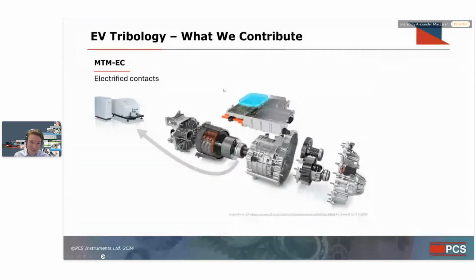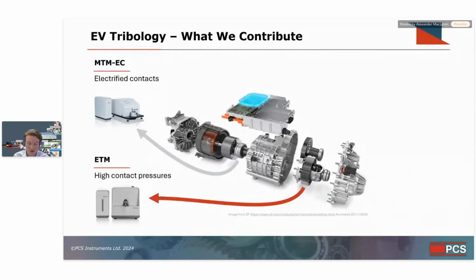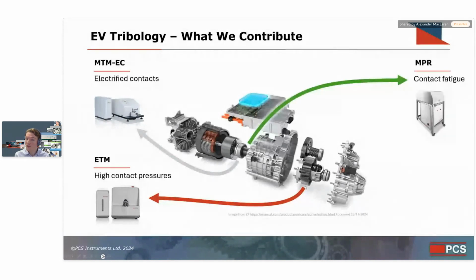And as Amir has aptly pointed out, there are several significant challenges in the design and optimization of both EV fluids and electric drive units in EVs themselves. And these create a perfect storm for tribologists because we have high-speed bearings that are electrified potentially by stray magnetic fields. And so understanding how these work and how the lubricants behave for them is challenging. Equally, we have very high contact pressures, for instance, in the low-speed stage of a gear reducer. We have high cycle components that potentially could fail by contact fatigue as a result of many, many contact cycles over lifetime.